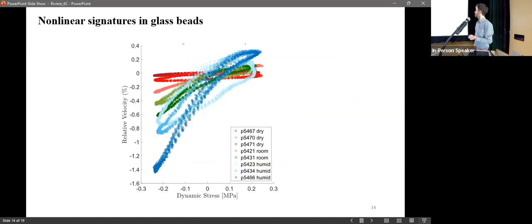Okay, so she has done this with glass beads. This is relative velocity change as a function of dynamic stress. When the stress is positive, this is compression. She's measuring the stress, so when it's positive, this is compression, and when it's negative, it's dilation. When she changes the relative humidity in glass beads, we see that for all the dry samples, the nonlinearity is much lower than for the humid sample. So you just change the relative humidity, it's making the grain junctions much weaker, and the nonlinearity is much stronger.